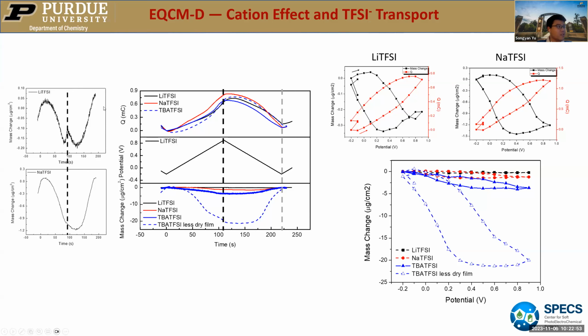What is also interesting is, zooming in on the lithium TFSI, during the de-doping process we can actually see a two-step mass change. At first, mass decreases with increased potential. That makes sense because we have lithium ejection from the polymer. And then we have a small increase here. So even in the de-doping process we now have a mass increase. It's quite understandable because TFSI also plays a role: we can see the anion injection in the de-doping process of lithium TFSI.